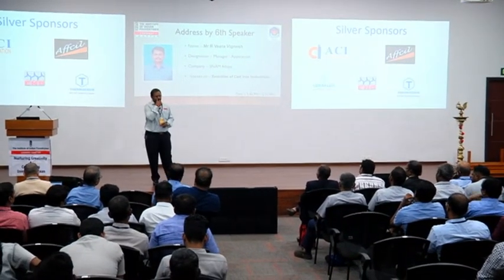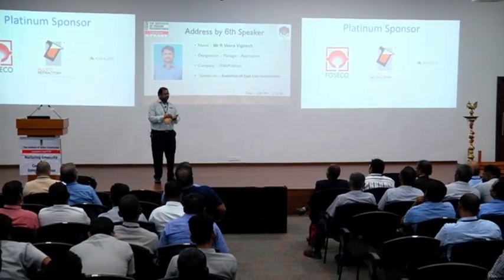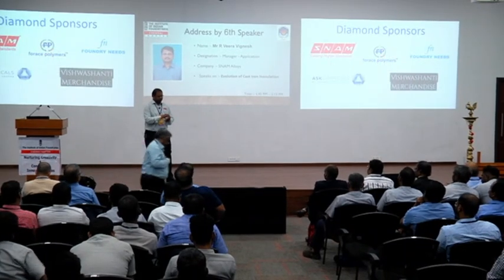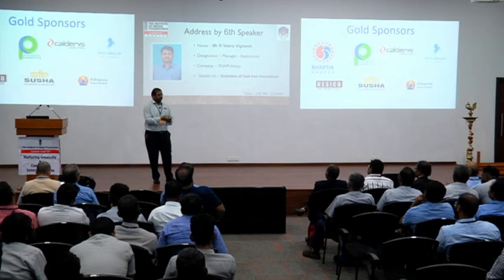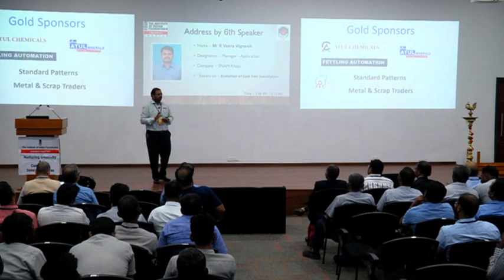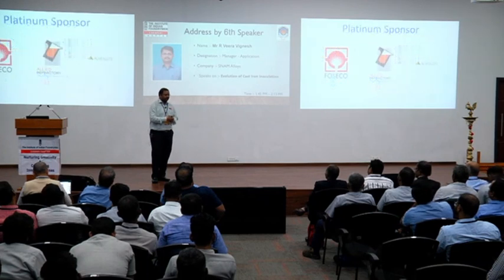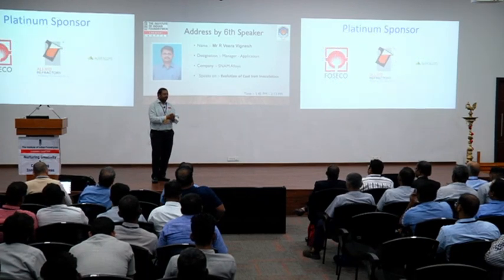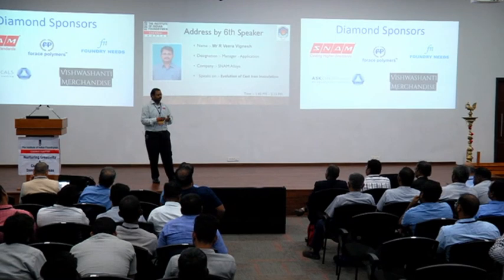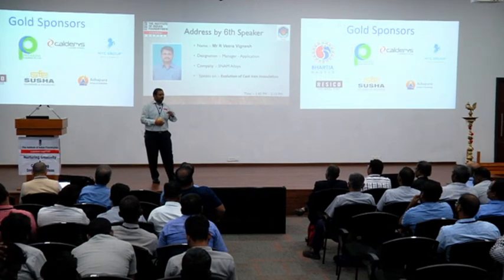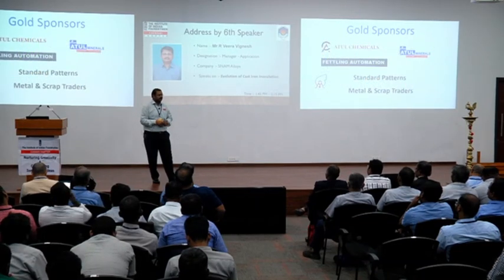Sir, any inoculant, say for example the aluminum inoculant, will have iron, silicon, calcium, aluminum. It can be other elements, or we need not have the other elements. If we have this four component system, the reactivity of your liquid metal and the oxidizing potential of these elements are to be looked into when I choose an inoculant. Say if I give you a barium inoculant, the amount of oxygen available in your metal or the characteristics of liquid metal might not be as compatible with barium's reactivity. There are some people who require aluminum, because aluminum has an equal or stable oxidizing potential as that of calcium and barium.